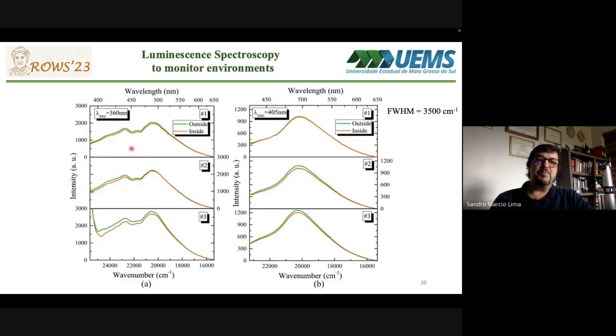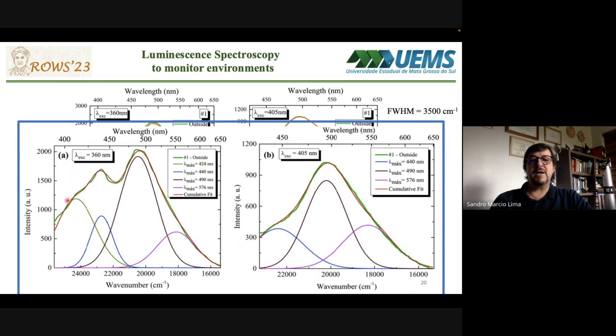So in this figure, we plotted the average fluorescence spectra that we obtained with the scales from streams number 1, 2, and 3 with these excitations. In green is the outside excitation, and the orange is the inside excitation. Following, we made a deconvolution of the spectra to identify the best Gaussian curves for fitting the experimental fluorescence data. In the literature, we found that the Gaussians centered here and here are mainly related to collagen, while those centered at 424 and 576 nanometers are due to the hydroxyapatite.